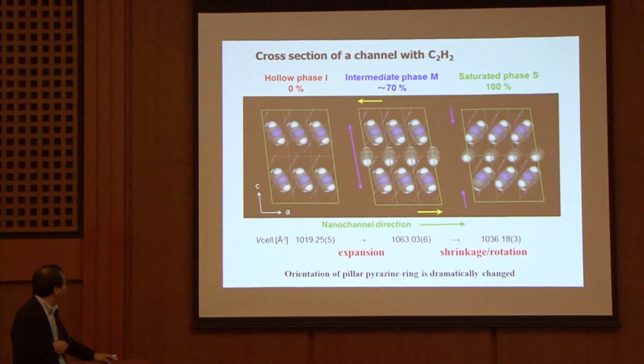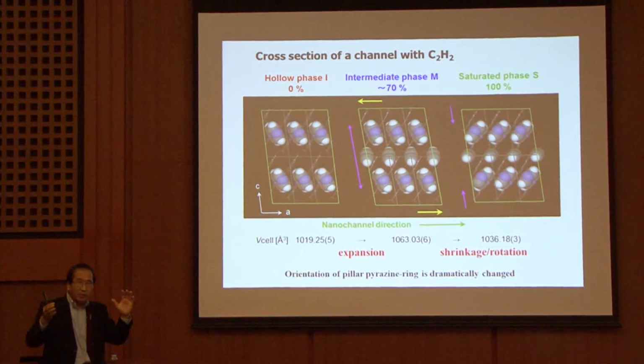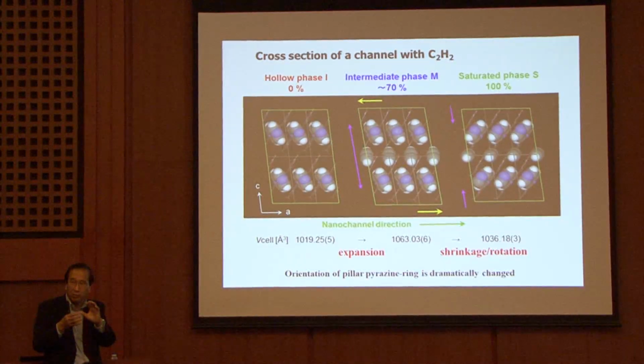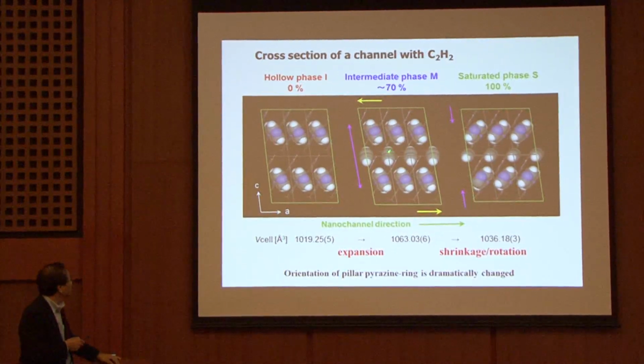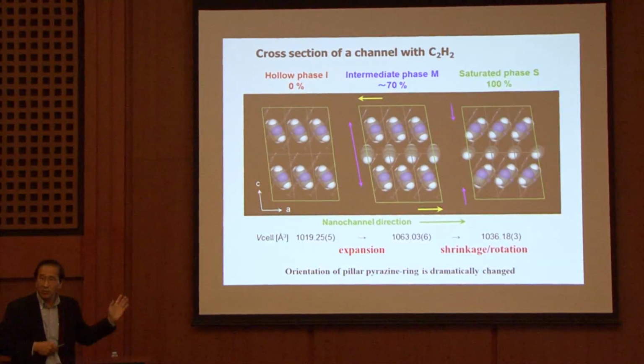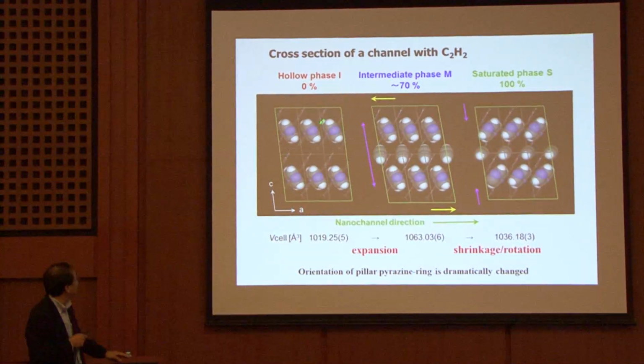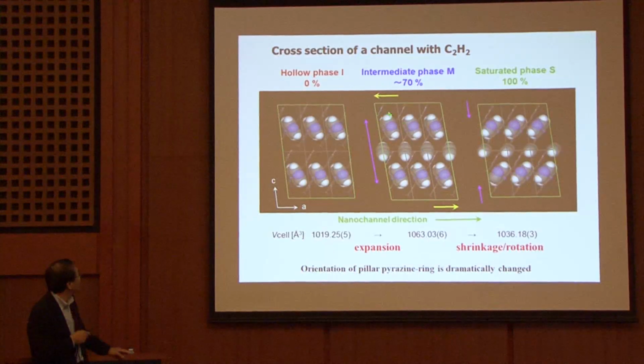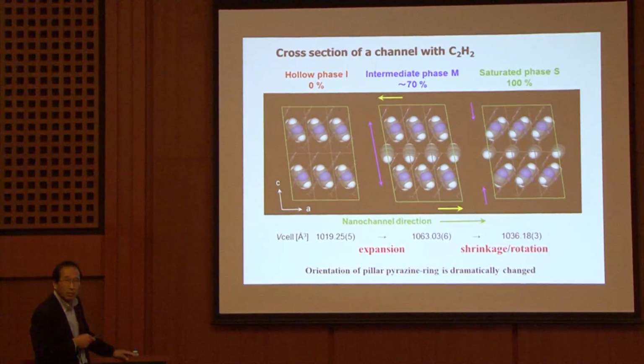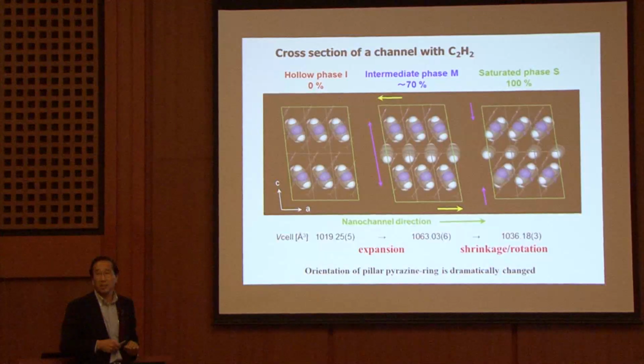You see, this is the volume here. And first, the structure expands to accommodate acetylene. And finally, shrinkage occurs in this case. Why so? Because the framework wants to have a close-packed interaction for the acetylene. So first expand, finally shrink. This is the mechanism. And another thing is this pillar ligand rotates from this direction to the other one. So this is a kind of small flexibility in this case.